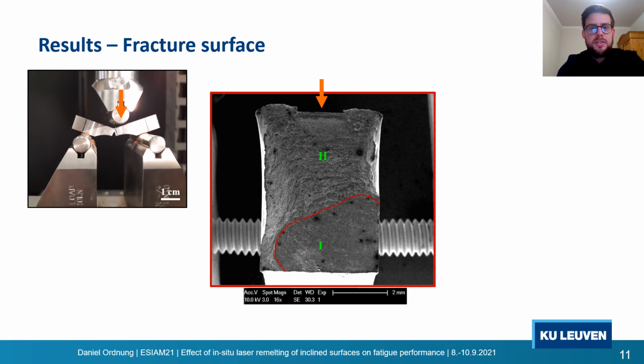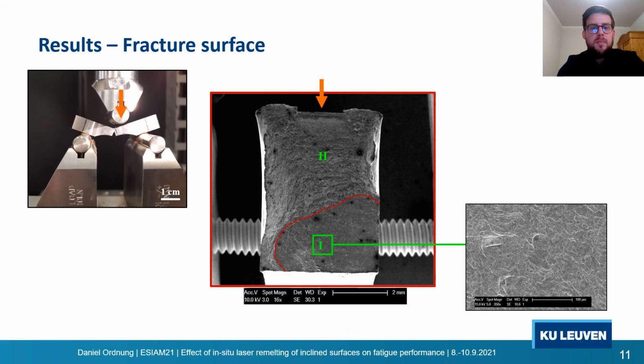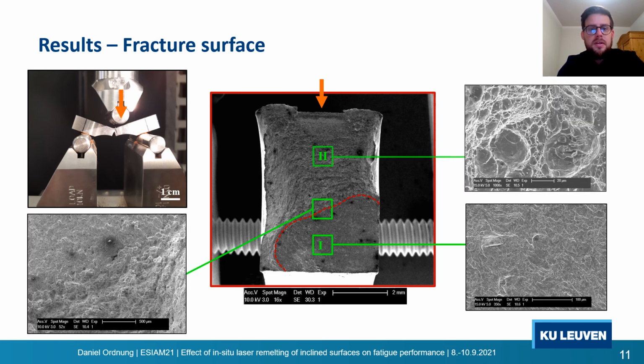Here we can see the first results for the fracture surface of a remelted maraging steel sample. We mainly can distinguish two fracture zones. There's the crack initiation and propagation zone, and then we see the final fracture zone. The final fracture zone shows dimples, which is a typical sign for a ductile fracture behavior. When comparing the fracture surface of the remelted sample with the as-built sample, it appears that with increasing stress level where the samples failed, also the final fracture zone increased.